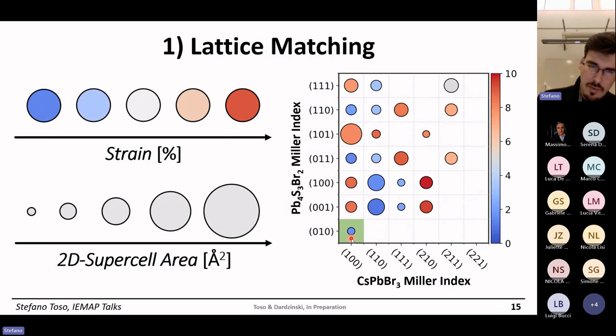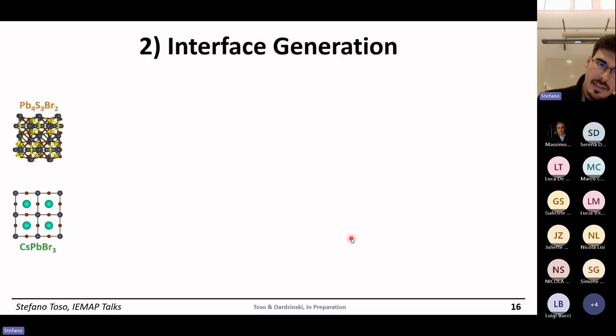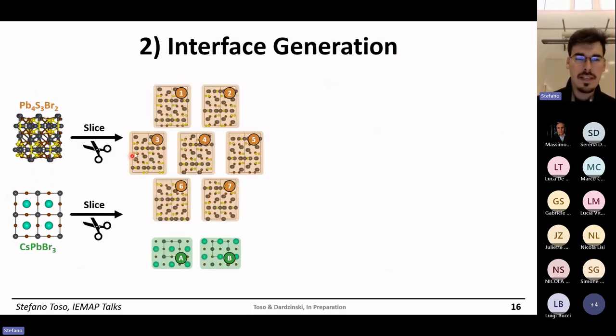You want to know the structure of a material. So what you do next is that you take your two compounds. You already know the relative orientation, so this is not taken by chance. And what you do is that you start cutting them at all the possible surface terminations. You create basically pieces of your puzzle, right? This material is simple. It can be cut at two levels, the lead bromide level and the cesium bromide level. This material is more complicated. You have 7 possible cuts.